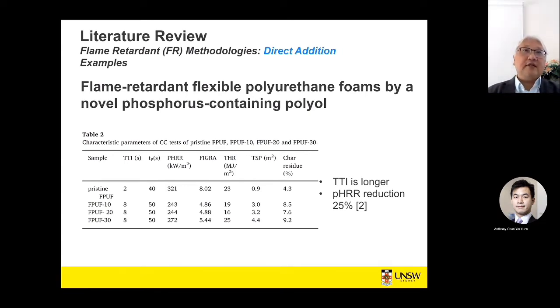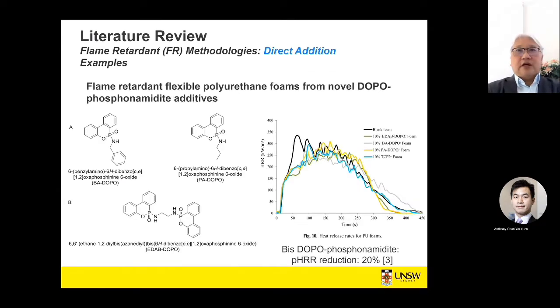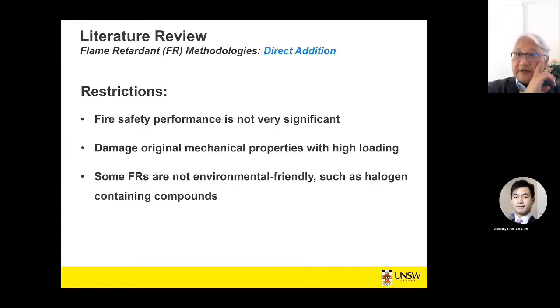So you can see that for the peak heat release rate, there's a 25% reduction, which gives us an indication that the introduction of phosphorus-based flame retardant could be a very effective way to flame-proof polyurethane. There are others, such as the introduction of other types of phosphorus-containing polyol like DOPO, which is very common. And it does give at least a 20% reduction in the peak heat release rate. Nevertheless, the fire safety performance remains not very significant, because with a 20% reduction the material will still burst into flames, and it's just a matter of retarding and not suppressing the flame spread that could happen.